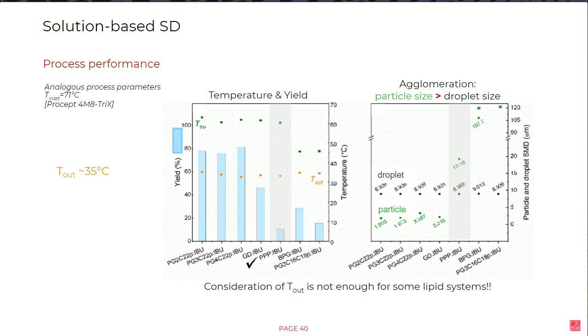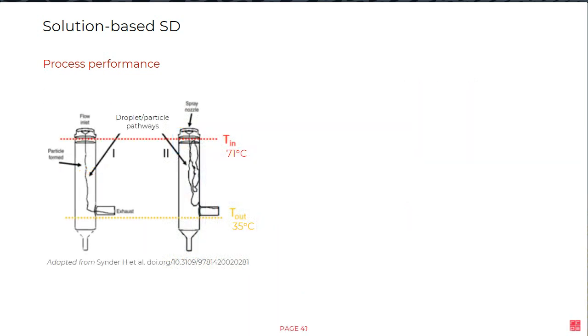How can we explain this, and how can we actually give solutions for this? Well, if we consider a simulation of the droplet and particle pathway inside the drying chamber, please now take a look at pathway number 1. This is the most straightforward and simple trajectory of a droplet particle. If we imagine at the inlet of the dryer the formation of a droplet, which is immediately exposed to the hot drying gas at 71 degrees, then the droplet will rapidly dry until eventually the solvent is completely evaporated and a solid particle is formed.